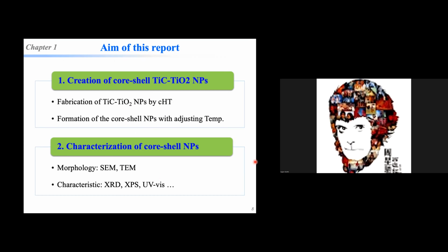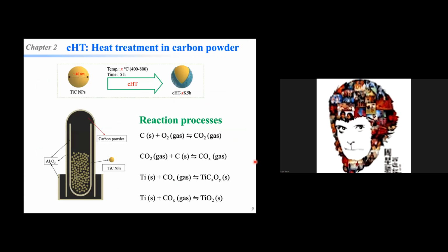in this report. About the experiment, we carried out heat treatment in carbon powder. The CHT is the heat treatment in the carbon powder. We just mixed the TiC nanoparticles with the carbon powders, and then heat treated them, and the possible reaction process can be summarized something like this.